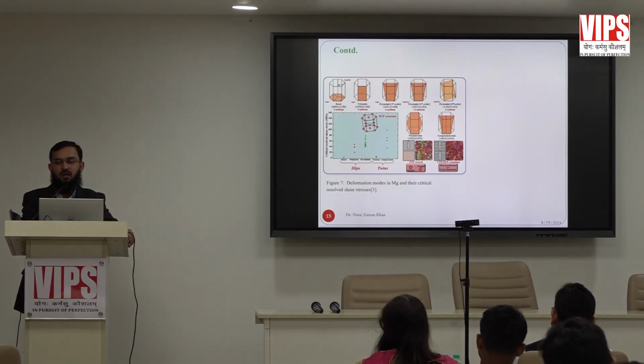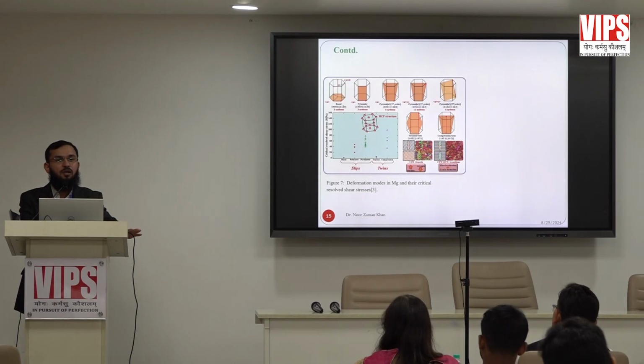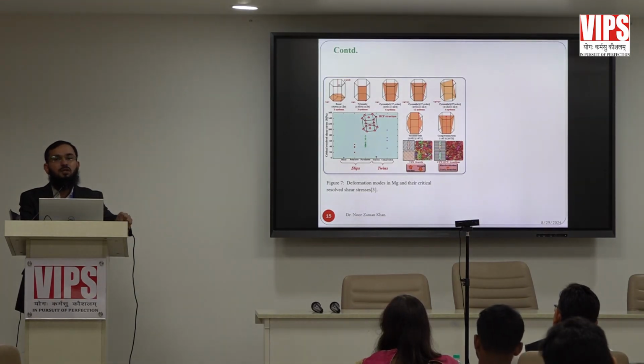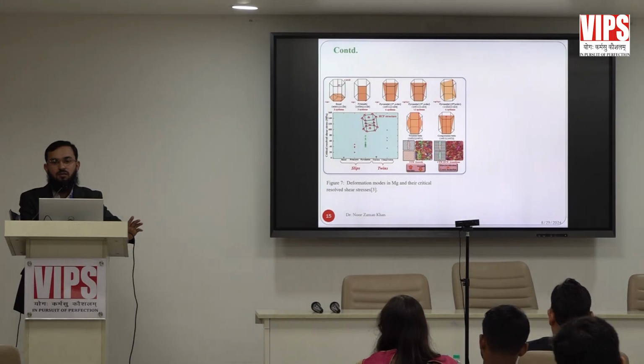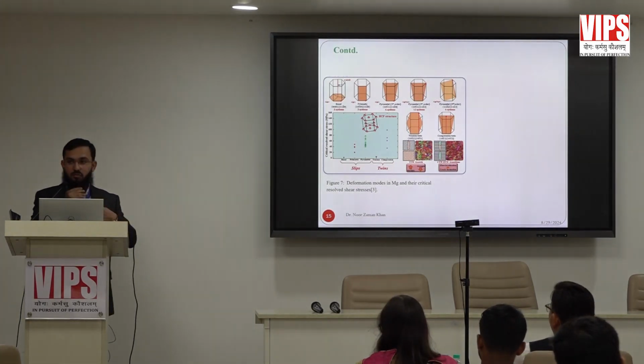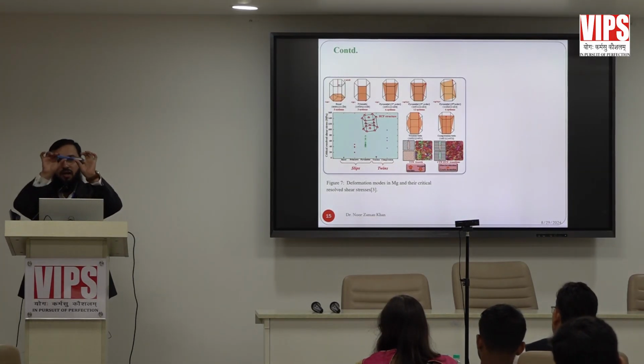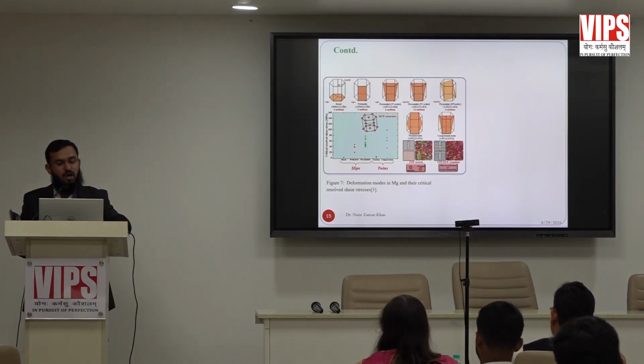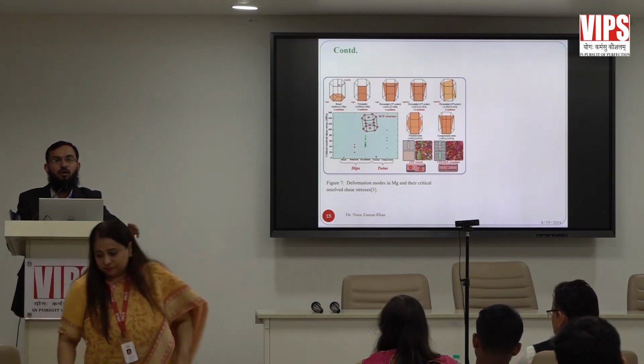It means that if you are deforming magnesium at room temperature, only one slip system is active, due to which you cannot deform it completely. It will lead to formation of micro cracks. Suppose you have a pen made up of magnesium, if you want to bend it, it will lead to the formation of some micro cracks. So the target is how to activate all slip systems.